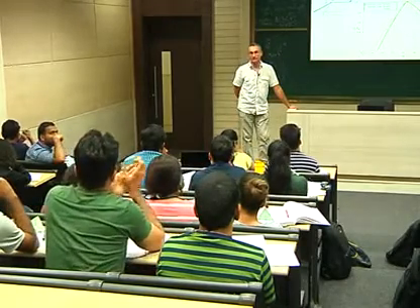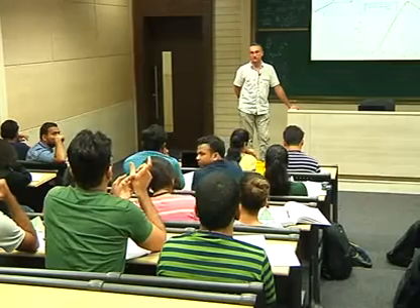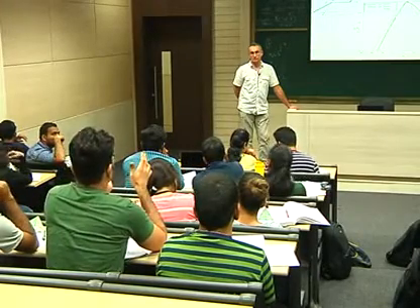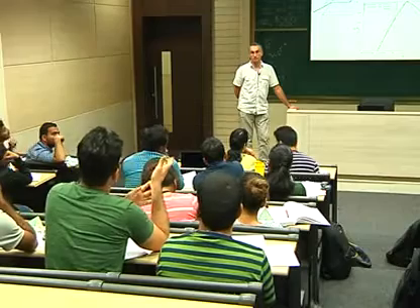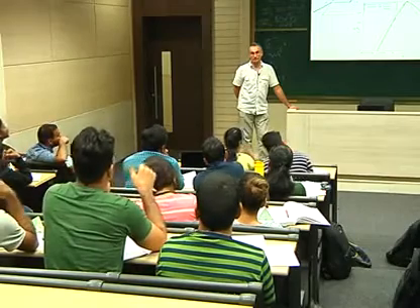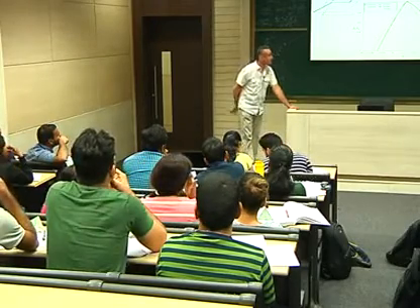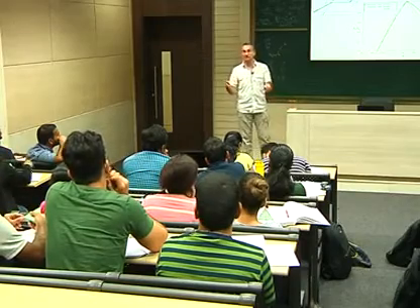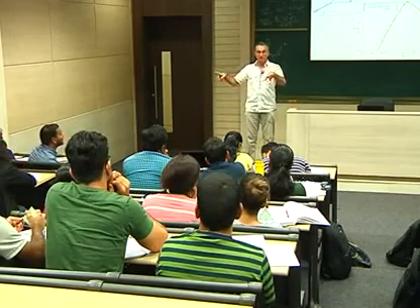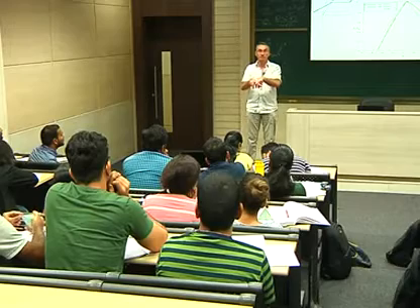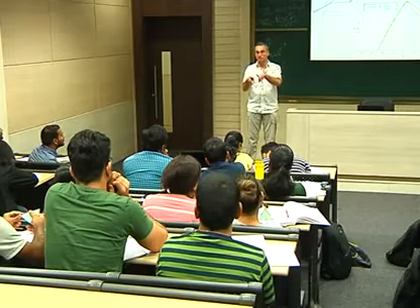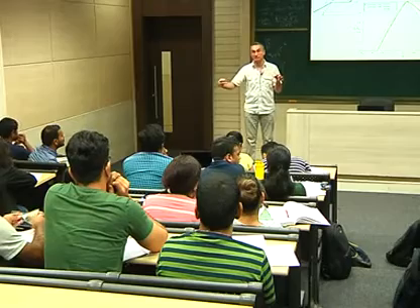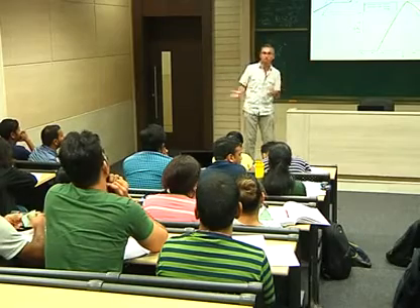In crystal plasticity, we model this self-hardening as well. Yes. So there will be some interaction which will occur in this same slip system. Yes, sure. So why is it not considered here? It is taken as zero. Because actually, here the junction will have a zero Burgers vector. If you have the same slip system, so same Burgers vector, if they want to meet and form a junction, it means B1 minus B1. If you put B1 plus B1, it repels. So it will be an annihilation, actually. So annihilation, do you call it a junction or not?